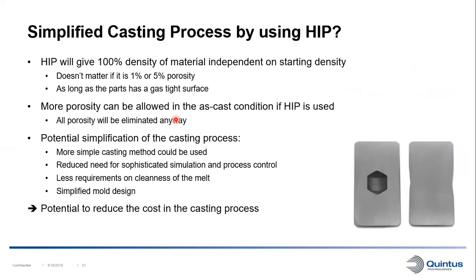So HIPing will give you 100% density of the material independent of the starting density. So to the HIP process, it doesn't matter if you have 1% or 5% porosity in your casting. It will still be 100% density in the end, as long as the parts have a gas-tight surface, which they have. So if we know that we're going to HIP, or that we decide that we're going to HIP, we could allow a higher amount of porosity in the casting, in the as-cast condition.